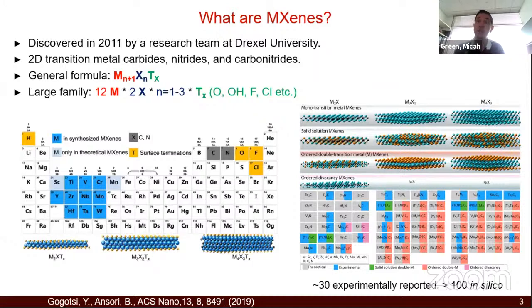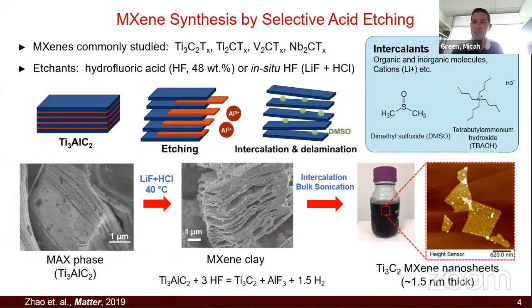People have simulated hundreds of these things, and at this point, probably about 30 have actually been made in practice. By far, the most common one is Ti3C2, titanium carbide. The way you make them is a little bit of a pain. You start with what we call the MAX phase. So you can see that here, M, titanium, A is aluminum usually, and then the C is X. So this is a layered ceramic phase. And what you do is you use acids like HF to etch out the aluminum. And once you do that, you get structures that look like this.